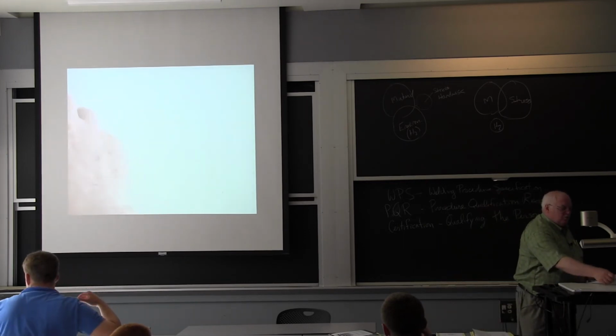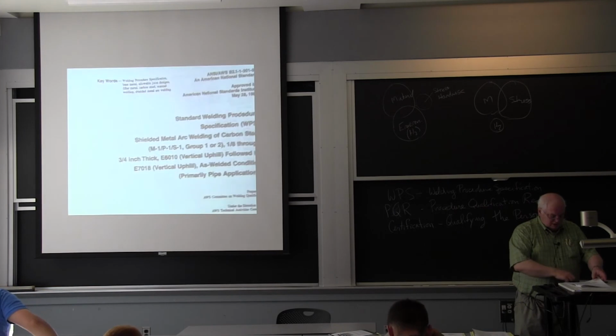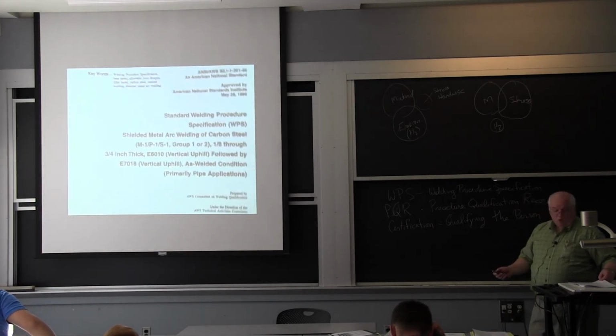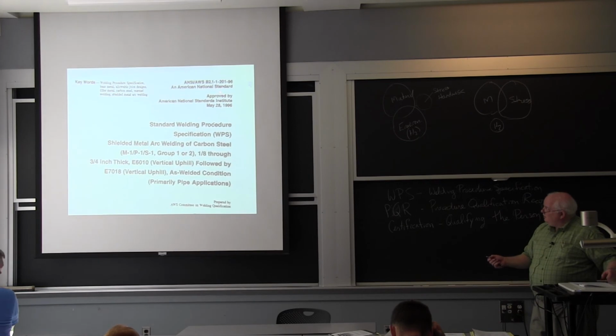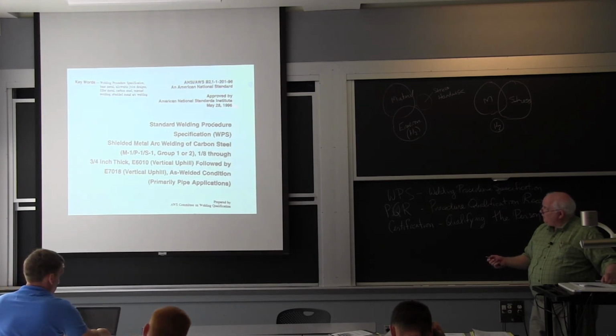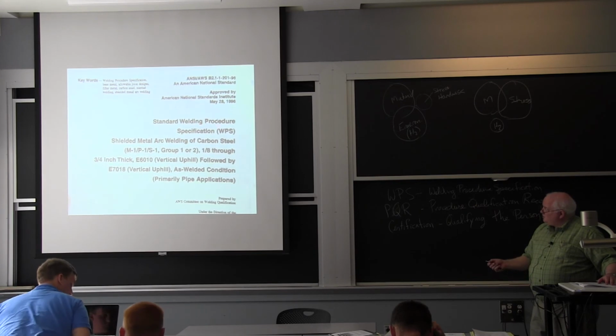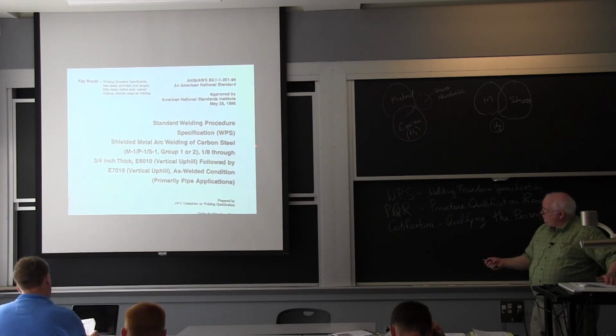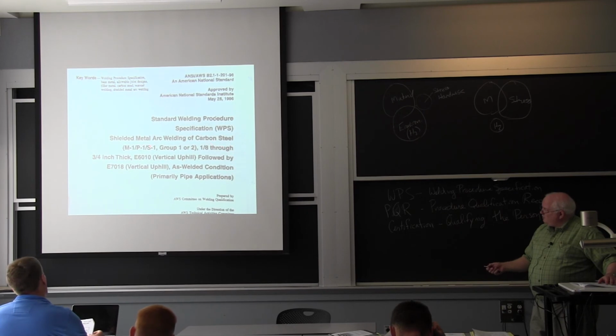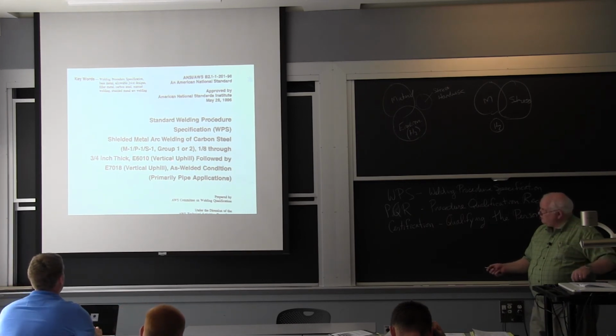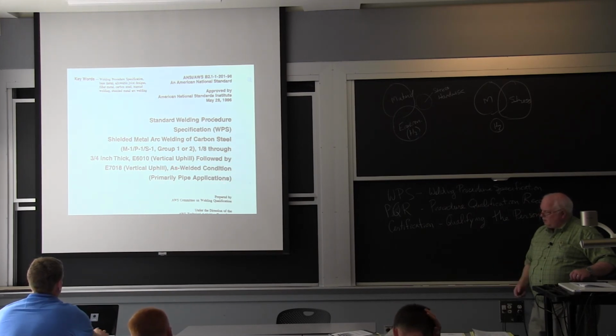And so if you want to spend $1,000 or $2,000, the AWS will sell you a pre-qualified code. And this is the code, May 28, 1996, Standard Welding Procedure Specification, WPS, shielded metal arc welding of carbon steel, and here are the different types of steels, okay? And then you have to go to the code to understand what those are. 1/8 inch through 3/4 inch thick, E6010 electrode, one of these cellulose electrodes, vertical uphill followed by E7018 vertical uphill, as-welded condition, primarily pipe applications.